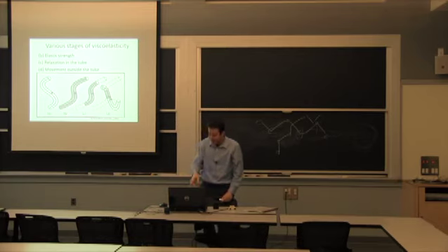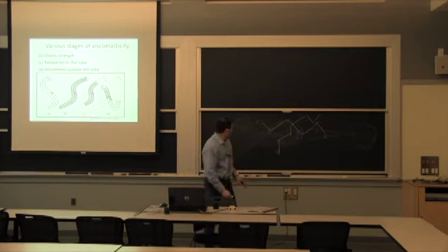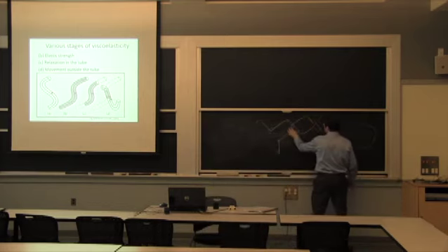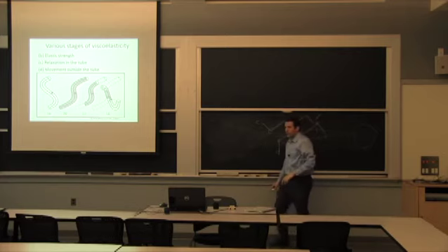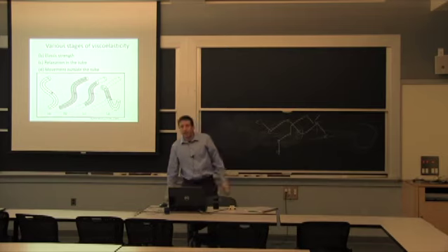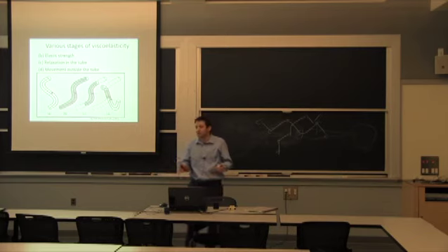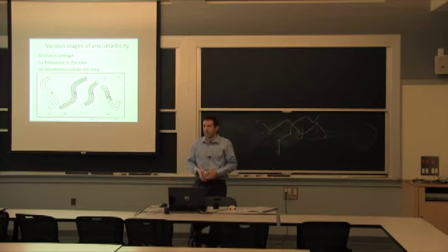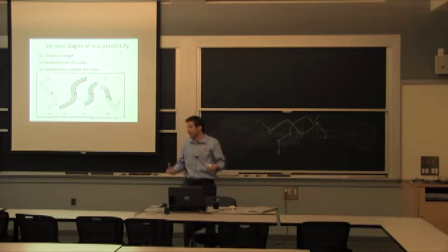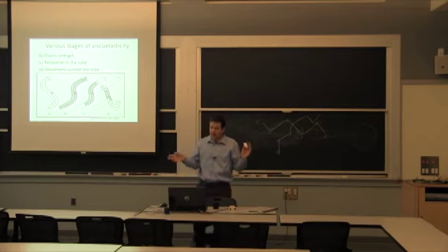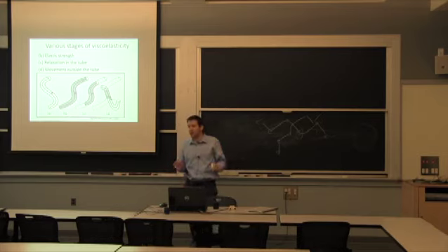What happens in D is what some people will call viscoplasticity or permanent creep, where now, when we had our two chains here, we can actually take this one and move it further. And that is becoming very complex to think of, because if you reheat the plastic, I've seen experimental results where what we consider a permanent deformation will actually reverse on you. So there's a fine line. There's always going to be some history in the material, and the distinction between C and D, to me, is maybe there, but it's very limited. It's more limited than people think.